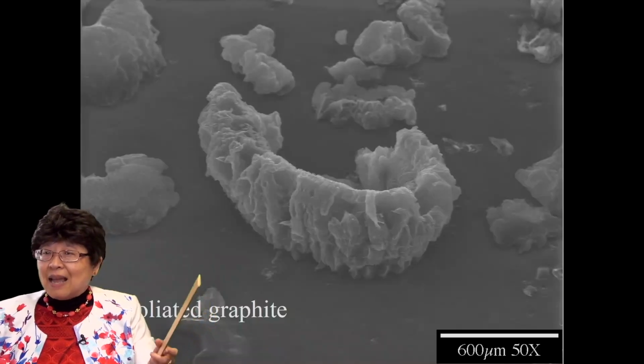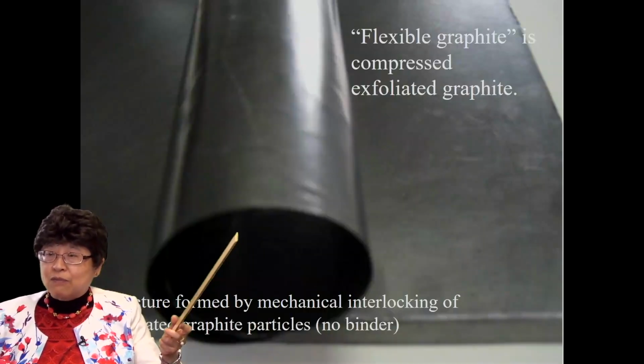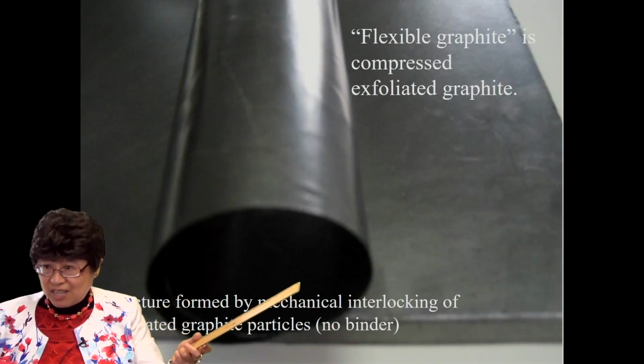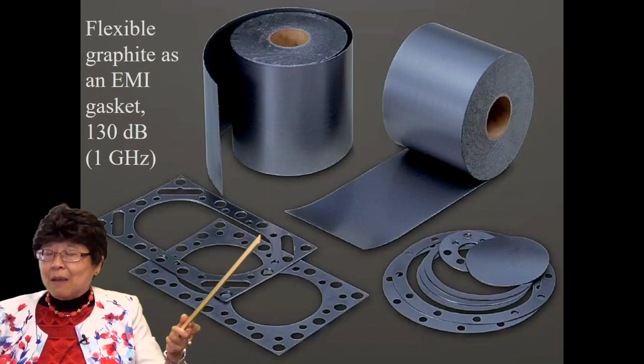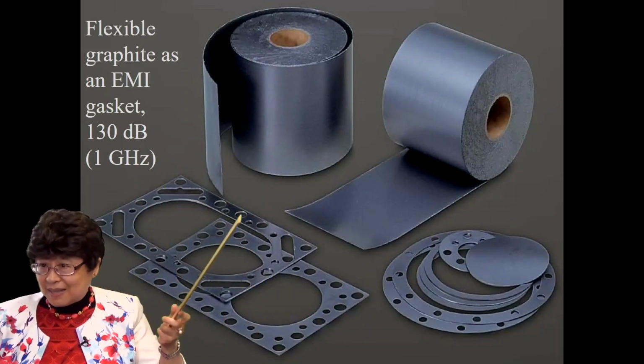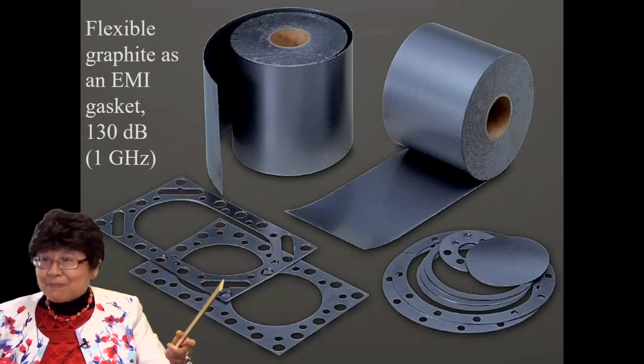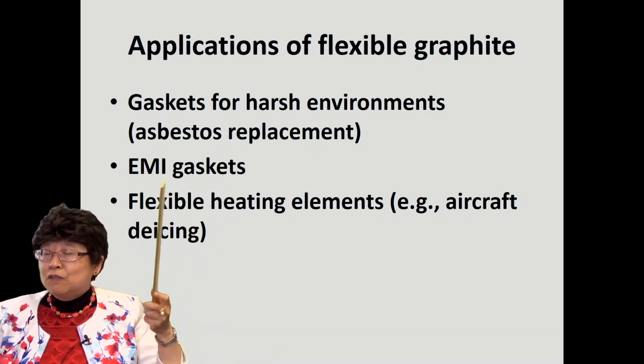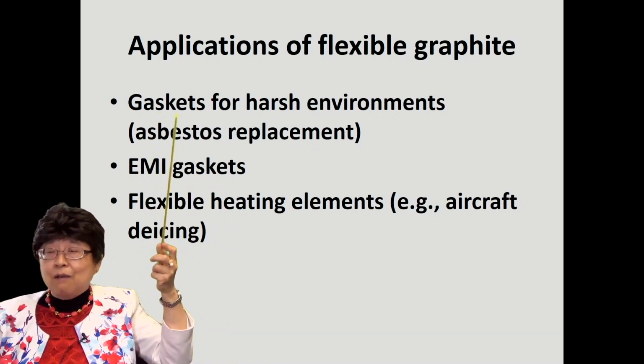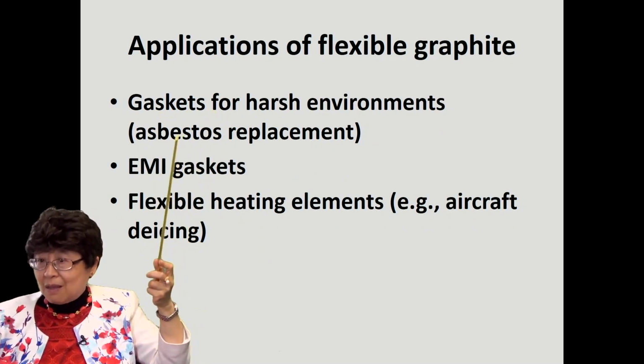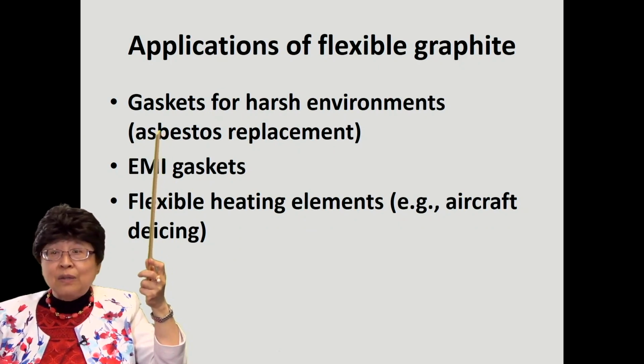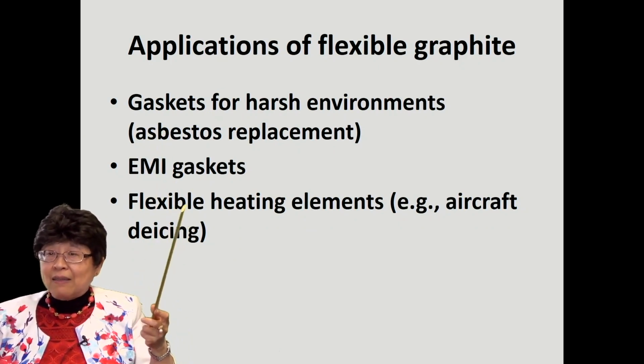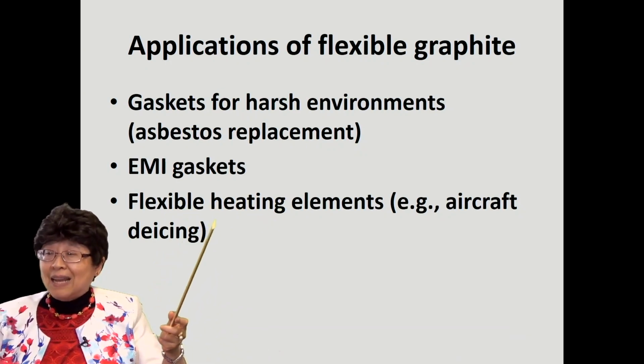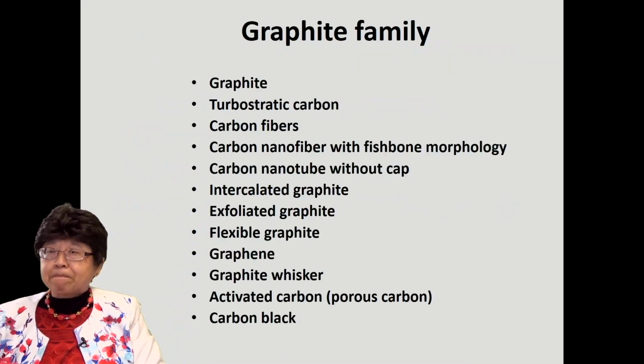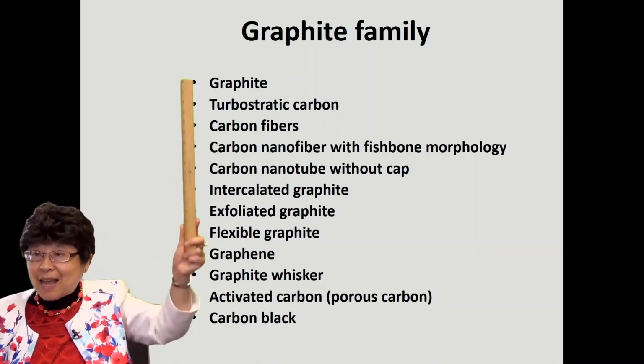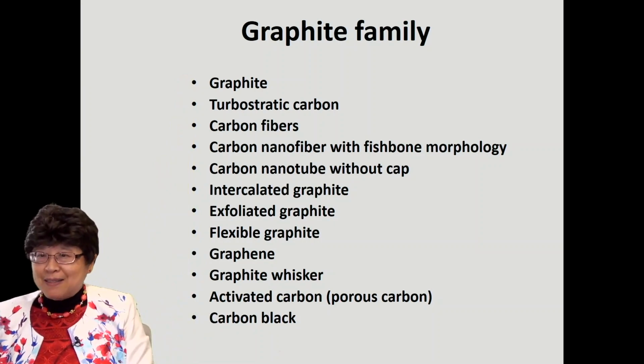Flexible graphite is next, and that is formed by having a pile of exfoliated graphite and compacting it to make a sheet. Because of the resiliency, it is good for EMI gasketing. Okay? And you can cut it using scissors. Applications involve not just EMI gasketing, but also regular gaskets for harsh environments, for asbestos replacement, because graphite is relatively inert chemically. Also, because of the conductivity and the flexibility, one can use it for flexible heating elements, such as for aircraft de-icing. So this completes our discussion of all these members of the graphite family.